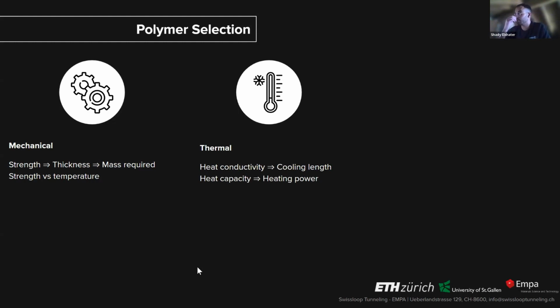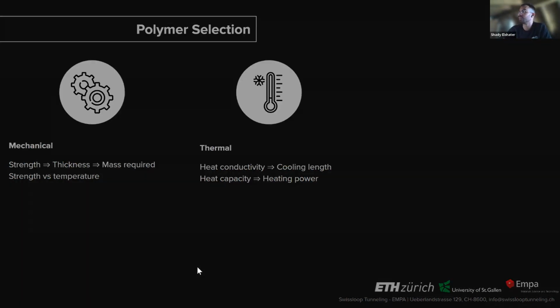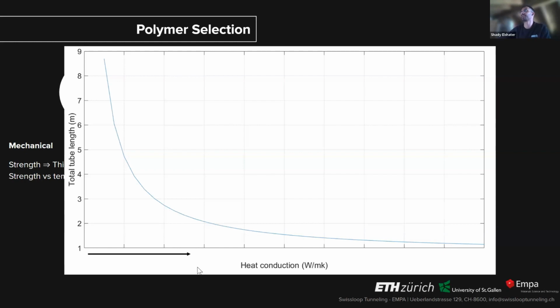From the thermal point of view, the heat conductivity of the polymer affects the cooling length a lot. I also have a plot afterwards. Then the heat capacity clearly affects the heating power, so how much heat you need to give, both in terms of the extruder and in terms of heating elements. Just to give you an idea, here is a plot that we generated with our model for the cooling of the polymer. This takes into account the polymer, which starts in liquid form and then is brought down to solid, and then down to the structural temperature.